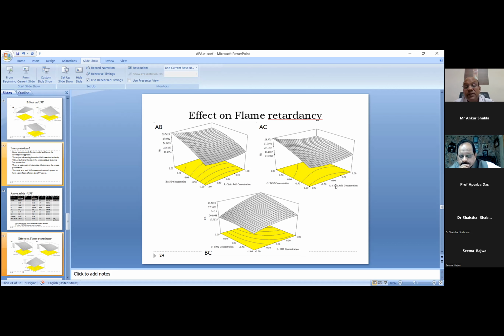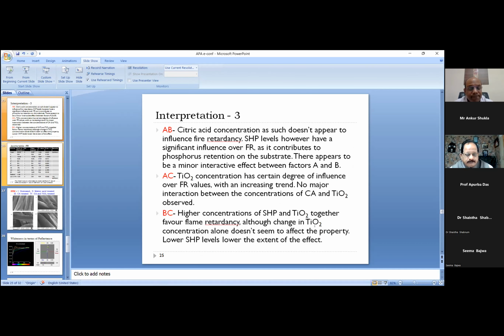And again, in citric acid and TiO2 concentration, citric acid, if you see, it doesn't have much of an influence. It has a minor influence, but doesn't have much of influence on the FR. It has a certain amount of influence because the possibility of cross-linking will also increase if you have higher concentration of citric acid. So that is how it is contributing. And here also we find that with increase in SHP, there is an increase in fire retardance. So this is the interpretation, the one that I just told. So that is put in words here.